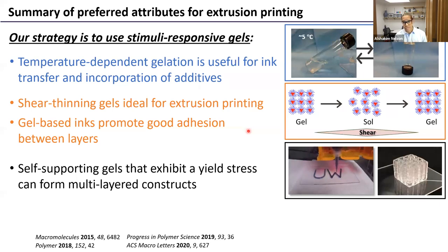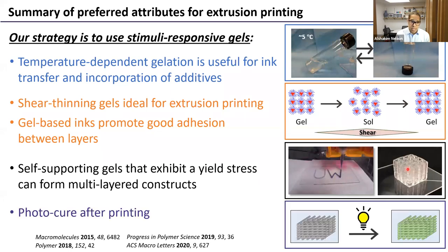But once we've extruded, these filaments have a sufficient yield strength such that the gels do not continue to flow over time. And that allows us to create these multi-layered constructs of these gels. And then finally, we do a photo cure at the end. What I mean is that after we've printed the entire construct, then we come back and we irradiate with light, and that initiates a radical polymerization of those methacrylate groups, the chain ends of the polymer, and now that permanently fixes the gel so that we get these robust constructs.